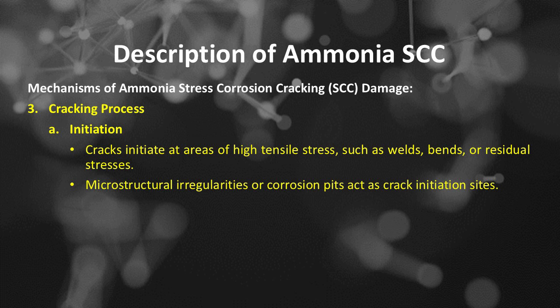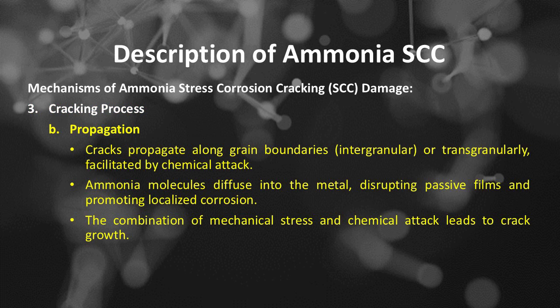Number 3 of mechanisms of ammonia stress corrosion cracking damage is the cracking process. Number A, cracks initiate at areas of high tensile stress, such as welds, bends, or residual stresses, and microstructural irregularities or corrosion pits act as crack initiation sites. Number B, cracks propagate along grain boundaries, intergranular, or transgranularly, facilitated by chemical attack. Ammonia molecules diffuse into the metal, disrupting passive films and promoting localized corrosion. The combination of mechanical stress and chemical attack leads to crack growth.